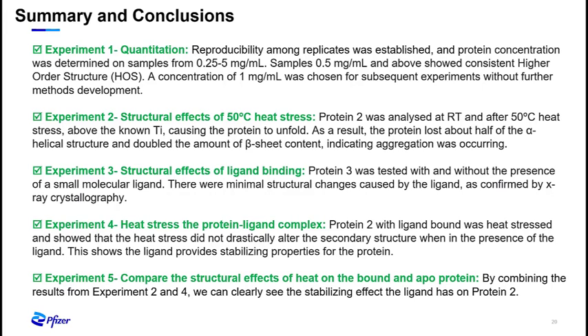Our third experiment, we looked at structural effects of ligand binding. Protein 3 was tested with and without ligand bound. Here, there were minimal structural changes observed by binding of the ligand, and this has been confirmed by X-ray crystallography, where we didn't see many changes there either.